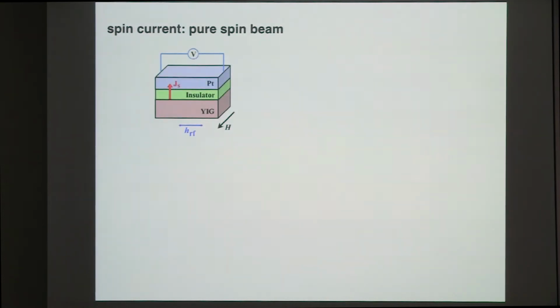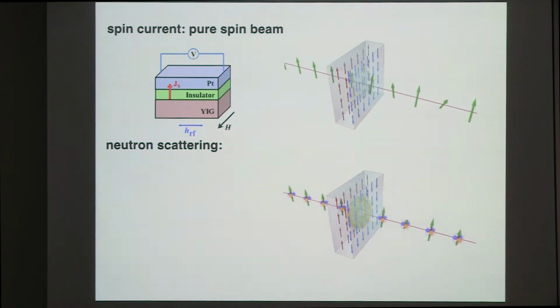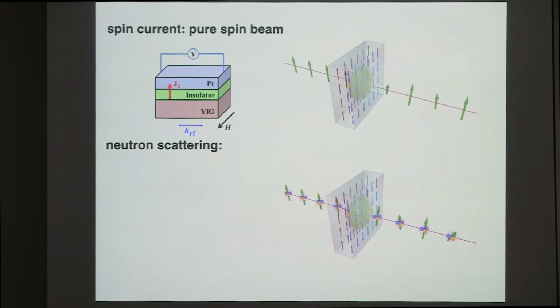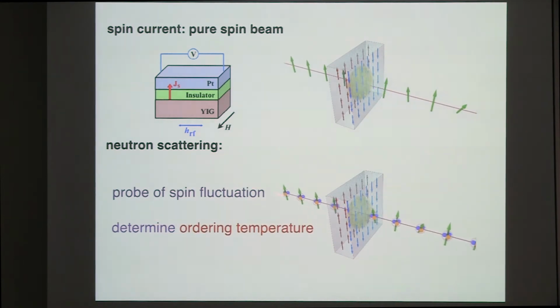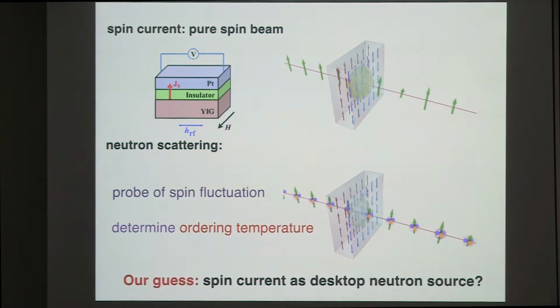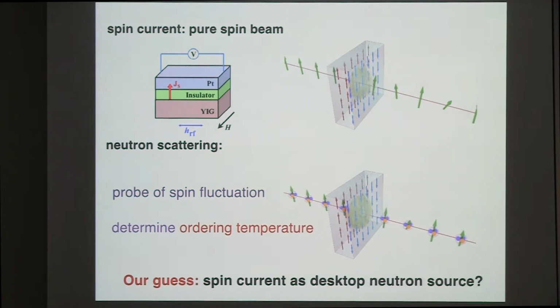But later on, we took a closer look at the data. We find that if we look at the spin injection in this kind of structure, you can abstractly imagine that it's just the flow of angular momentum going through this antiferromagnet. This process is pretty similar to neutron scattering. So we drew these two cartoons, just putting some balls mimicking the neutron. For neutron scattering, we are pretty sure that we can probe spin fluctuation and determine ordering temperature with these kinds of particles. Since that looks quite similar, we guess that the spin current can also probe the magnetic fluctuation, the dynamics in the antiferromagnet, a little bit.